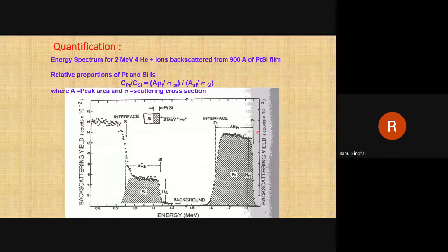From this, now your aim is to find out the information quantitatively. Information means what elements are present, what their elemental concentration will be, what their depth will be, all these things. Because once you perform the backscattering measurements, you will simply get raw data like this. Now you can see we have platinum and silicon in our sample. Obviously silicon is lighter. I told you if your atom is lighter, then it will lose more energy in collision. So the backscattered ions that collide with silicon will have less energy. You can see in this figure, this is the silicon peak, coming at lesser energy compared to platinum. The platinum peak is coming from 1.6 to 1.8, and the silicon peak from 0.9 to 1.2. So the peak at lower energy will be of silicon, and the one at high energy will be of platinum.